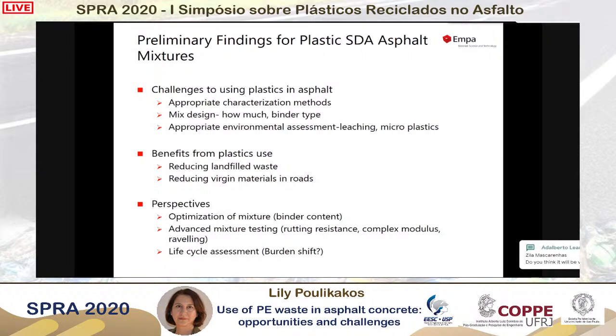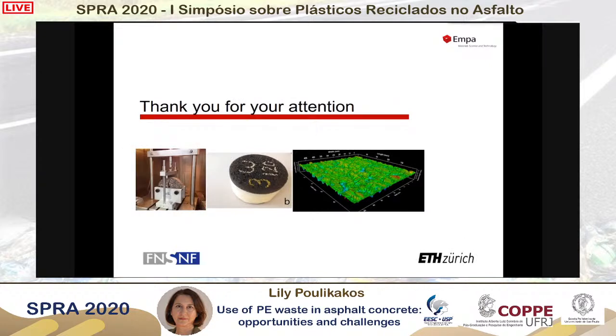We are hoping then to optimize the mixtures in the future. Binder content and binder type are very important. Also, other mixture testing methods, looking at rutting and complex modulus and raveling. The special mixtures that we're using, the SDA, have a raveling problem, so it's important to have the right experimental methods to mimic the raveling they experience in the field. Of course, the life cycle assessment I mentioned several times, and the whole idea of a burden shift. So that brings me to the end of my presentation, and I thank you for your attention, and I look forward to answering any of your comments.